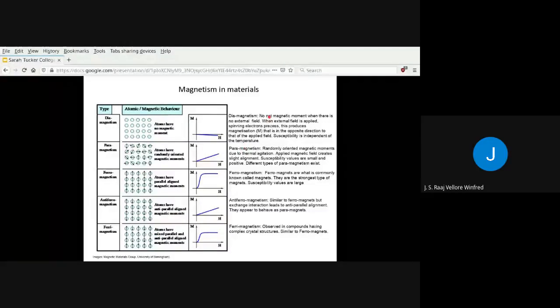Okay, so here you can see different types of magnetism that are commonly observed in nature, starting with diamagnetism. In diamagnetism, your atoms have no magnetic moment, which means that when there's no external field, there's no magnetic moment. This phenomenon is observed when you apply an external field. When you apply an external field, the electrons precess, and this produces a magnetization. This magnetization is opposite to the direction of the applied field, and typically the susceptibility is independent of the temperature.